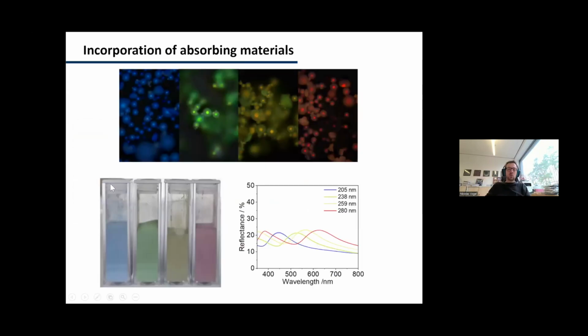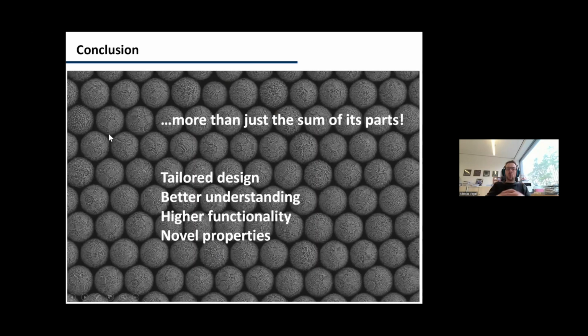And now we can also play around with the size of the primary particles, and this allows us to make structurally colored pigment throughout the entire visible range. So you see the color macroscopically, you see it even better, and you can analyze it much more conveniently under a microscope, and we can measure the spectra that really corroborate the photonic stop band and the macroscopic color that we see. And with this, I'm at the end of my talk, and as a conclusion, I just want to